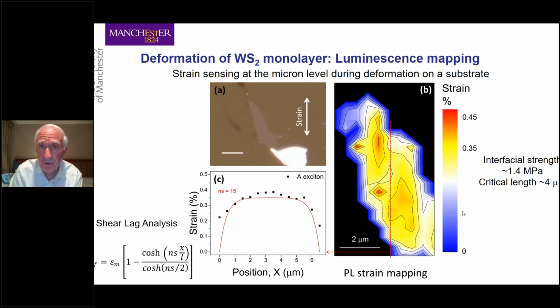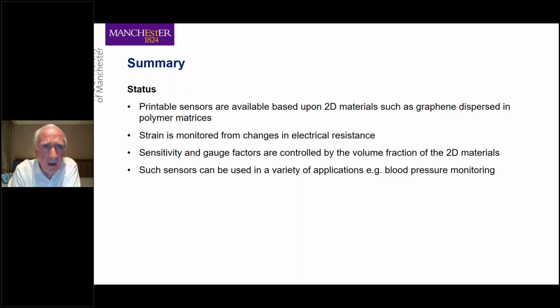And we saw in the first presentation how you can actually produce those sort of structures, which I found very interesting indeed. So I'm now coming just to the end of my presentation. With these 2D materials, as far as actual strain sensors are concerned, printable sensors are available by dispersing 2D materials at the moment. And in those sort of systems, you can measure strain from changes in electrical resistance. And you find that you can tune the sensitivity by the volume fraction of the material. And you can use these sensors for a variety of applications. The one I showed you was for blood pressure monitoring, but there are various other applications where you can use them.